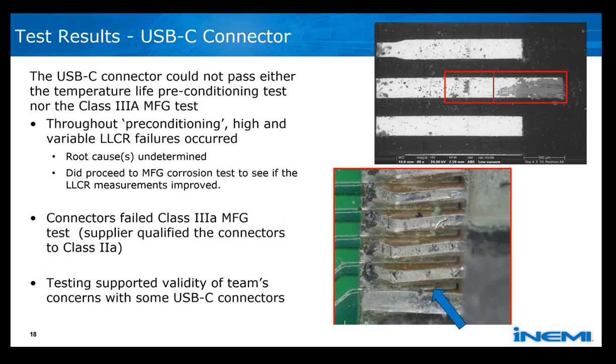But we decided to continue into the MFG corrosion testing to see, did the failures continue? Did some of the failures go away, which can sometimes occur due to the mate-unmate that occurs during the gas corrosion testing for the contact resistance measurements, and to see what the data showed us. When we examined the samples after temp life, we really didn't see any root cause for the high resistance readings.